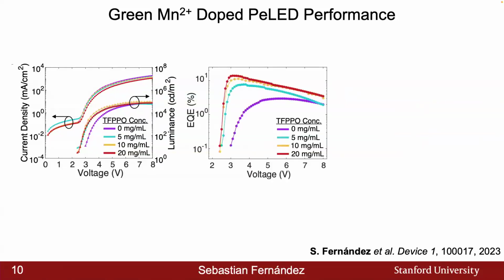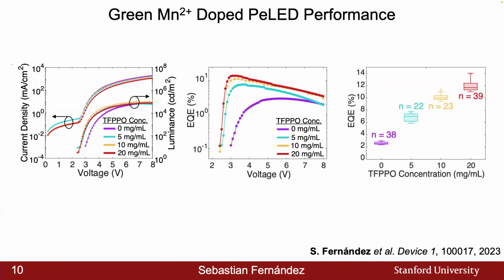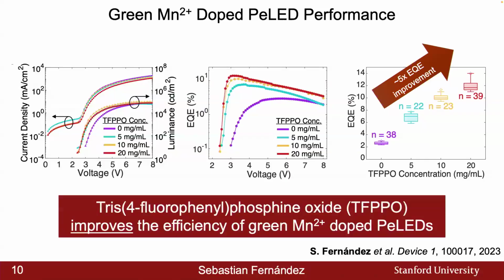If we now look at, again, the figure of merit, EQE, for device efficiency, we can see that with TFPPO concentration, we can monotonically increase the EQE to a new record of 14.0%. And in order to ensure the validity of these claims, we can also look at the device statistics. And across 120 devices, we can see an overall 5x improvement in the EQE, which makes us confident to say that we're definitively improving the efficiency of these devices by using TFPPO.